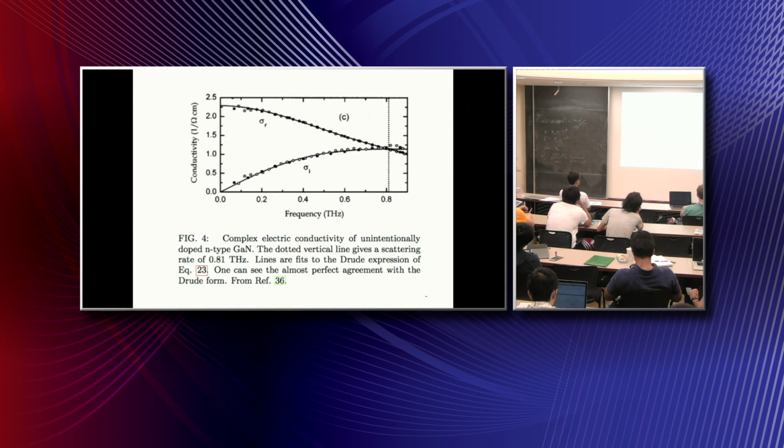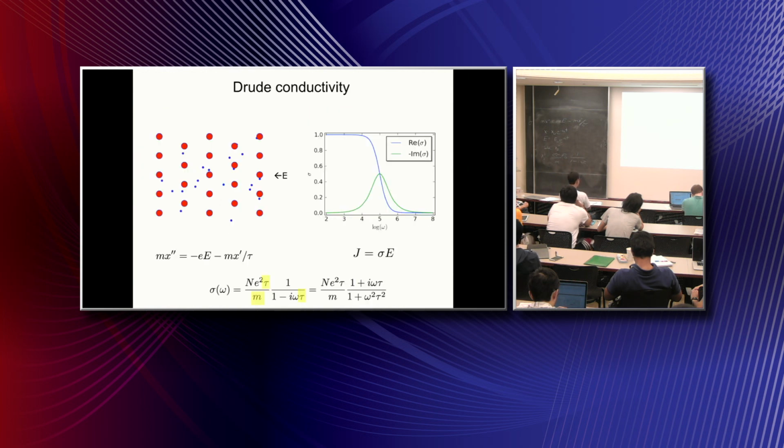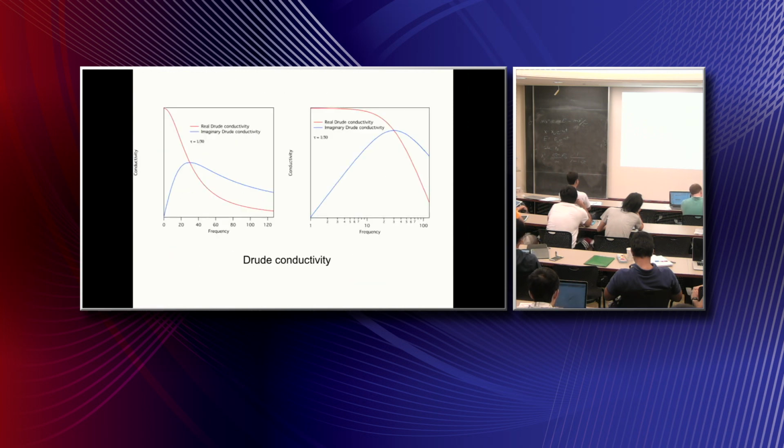As we're going to talk about in the case of superconductors, it's actually the imaginary part of the conductivity which has most of the interesting information in it, and the thing that we can really measure. The relative sizes of the real and the imaginary parts tell us something about the relative scattering rate. By inspection of this term here, and realizing that the imaginary part gets larger than the real part at some characteristic frequency, that's 1 over tau itself. Okay? So just from inspection of these plots, I can figure out the scattering time of an electron as it moves in some particular material.